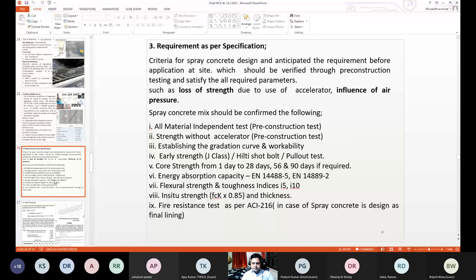Criteria for spray concrete. The designed and anticipated requirement before application at site should be verified through pre-construction testing and satisfy all the requirement parameters, such as loss of strength due to use of accelerator and influence of air pressure. The following tests are to be done while pre-construction testing, or we can say before use at site: all material tests, independent tests, the strength without accelerator to be established, establishing the gradation curve and workability, early strength, Hilti shot bolt and pull-out test.